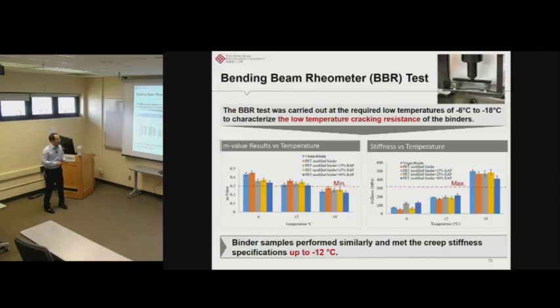If we take a look at these two plots, in terms of the M value, after we add the PET additive, which is the second one, the M value is slightly increased, and the stiffness value is slightly decreased. Both are good for the binder's low temperature cracking resistance. If we further add the RAP binder, compared with the virgin binder, there is not a significant difference in both M value and stiffness. In other words, it will not change the low temperature grade of the virgin binder.